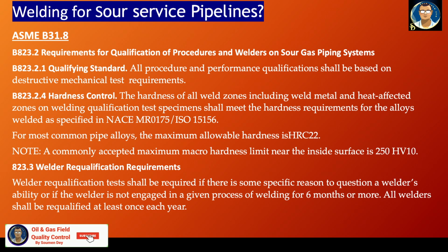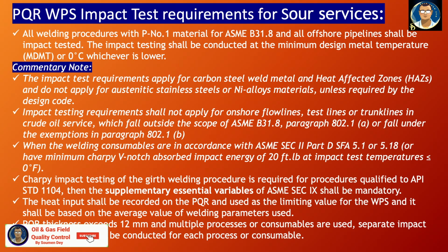Hardness also needs to be controlled as per NACE MR0175 and ISO 15156, and the maximum allowable hardness for the common pipe alloys is HRC 22, and if you do the macro hardness, the limit is 250 HV10. Welder should be requalified within 6 months if he is not engaged in the job continuously, but at least once yearly, they should be requalified from the client approved third party company.